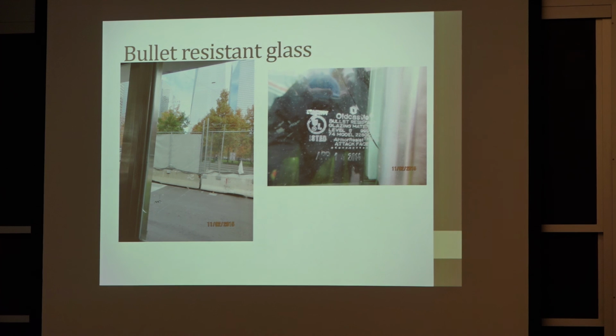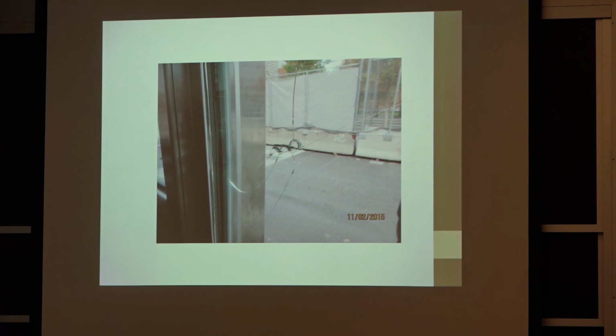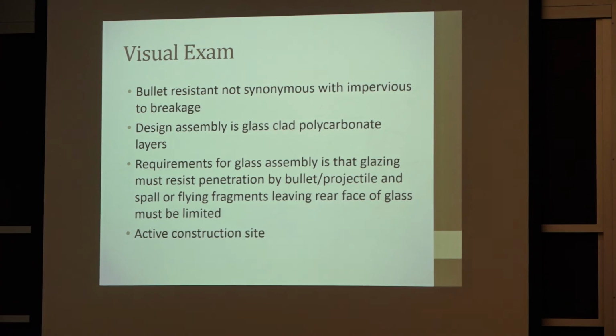The last one I want to get to is bullet-resistant glass. This was at a site I was at a few years ago, and they wanted to know if there was an issue with the glass because they had a couple areas where there were nicks in the glass and slight areas where the bulletproof glass had indications that something hit it. So they wanted to know what was wrong with their glass. Now, one of the things to note is bullet resistant is not the same as saying the glass is impervious to any type of breakage.